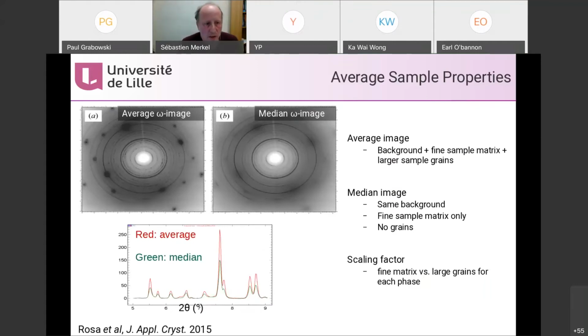Based on those images, you can actually even get a first set of information, because the average of all of those diffraction images includes the signal from everything: large grains, background, small grains, whereas the median image includes background and small grains, but not the large grains. And so this tells you something about your sample. If you do an integration of that image and plot the intensity versus 2 theta, the ratio between the two sets of intensities tells you how much of your sample is in the form of grains and how much is in the form of a fine powder, which you can't see.